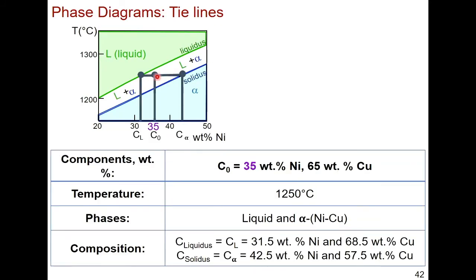Okay, here we go. Here's a good example. So I fast forwarded to your question. If you are at 35 weight percent, so C naught is 35 weight percent nickel. If this is what's in your system, you have 35 weight percent nickel and 65 weight percent copper. Right? 100 weight percent now. That's your system. To answer your question, the composition of how much nickel is in the liquid phase versus how much nickel is in the solid alpha phase are not the same. And you can determine them by drawing this isothermal tie line right here.